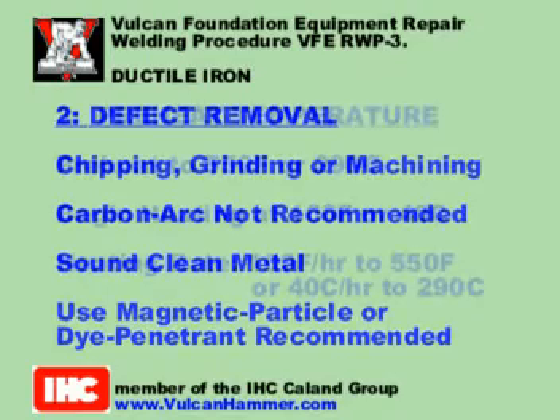Section 2, Defect Removal. The defect may be removed by chipping, grinding or machining. While carbon arc may be used on ductile iron, it is not recommended due to thermal shock and the formation of carbide martensite structure on the surface of the cavity. It is important that the weld cavity consist of sound, clean metal. In critical areas, the use of magnetic particle or dye penetrant inspection is strongly recommended.